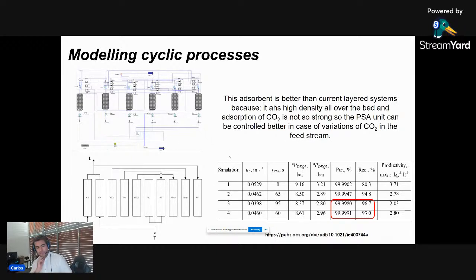And in this case, we demonstrated that with this cycle, for example, with pelletized UTSA-16, we can get a very high purity with a fantastic recovery and using only 6 columns, without the problem of using layers that is normally difficult to control, so that you don't pass the CO2 profile into the zeolite. And this will be a big benefit in terms of process control.